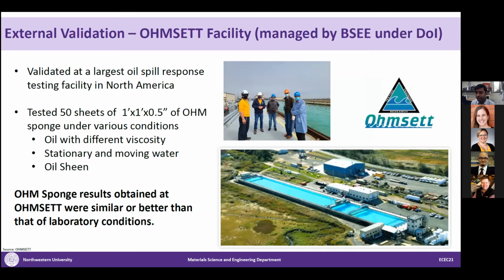To get external validation, we recently visited the OHMSETT Facility, which is the largest oil spill response testing facility in North America. We tested 50 sheets of this 1 foot by 1 foot by 0.5 inch OHM sponge under various conditions, where oil of different viscosity was tested, in stationary and moving water, and to test the oil sheen. And the OHM sponge results obtained at OHMSETT were similar or even better than the laboratory conditions. So this is the largest water tank to generate real-world applications for the OHM sponge. And we are quite happy that we passed their test also.